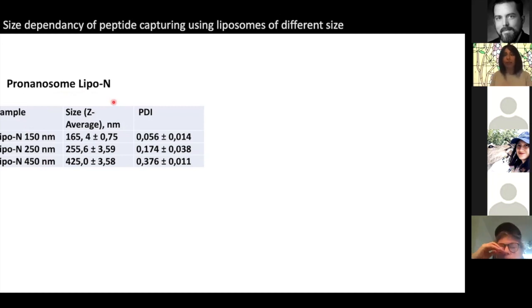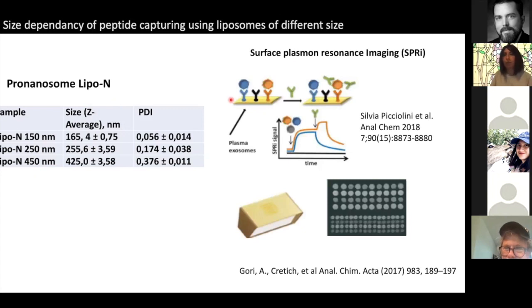NanoView instrument has a limited detection range, from 50 nanometers to just 200 nanometers in size in the large part of the size range. So in case we could not have detected the larger liposomes of 150, 250, and 450, we risk not being able to see them. So we used another detection technique, which is surface plasmon resonance imaging. It is a surface plasmon resonance detection platform coupled to imaging, SPRI.